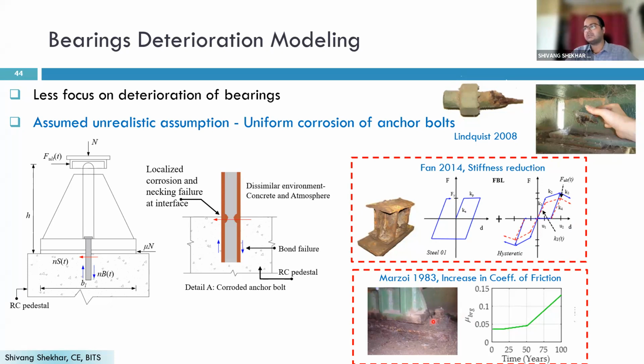So you can see some of the figures that talk about the frozen and locked bearings. So what it does is there is an increase in the coefficient of friction. The roller, which has to roll, due to the higher coefficient of friction caused by the corrosion, cannot roll.